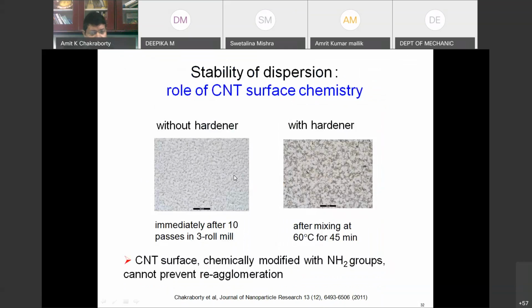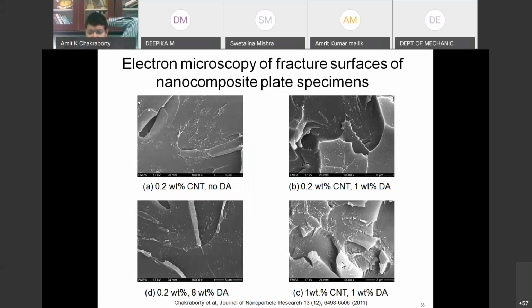Further, this is again a study of adding the hardener, without hardener and with hardener. This was done with chemically modified, aminated carbon nanotubes. NH2 groups were added to the carbon nanotubes. These are the fracture surfaces of the plates that we have cast. With this one particularly, you see a lot of carbon nanotubes because it has 1 weight % carbon nanotubes. The others have a very limited number of carbon nanotubes, but what evidences the breakage is a pull out, because you see the sharp edges, sharp white spots. Sharp white spots basically indicate that CNTs were also damaged.